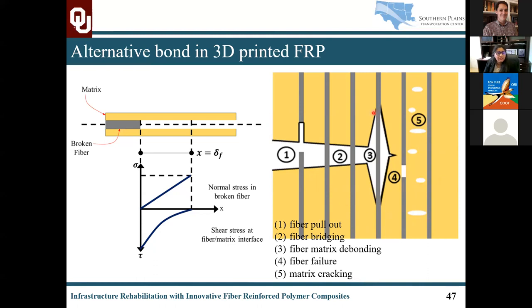These different kinds of failure mechanisms can be modified if the bond is affected and modified. For example, if there is a dampened bond between these two fiber layers due to a dampened and weakened interface of matrix modification, there will be different kinds of failures happening at that interface.